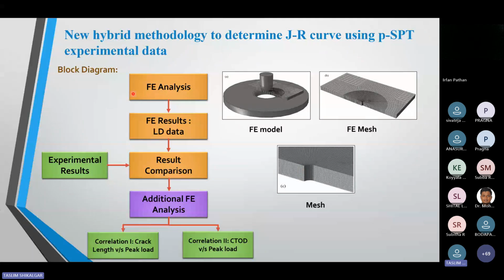Here I did the FE analysis of these specimens with the help of the tensile properties. And then I got the FE results from these specimens, only load versus displacement data. Here I compared my numerical results with the experimental results, and based on these comparisons, I developed 2 additional correlations. One correlation between crack length versus peak load, and the second correlation between CTOD versus peak load.